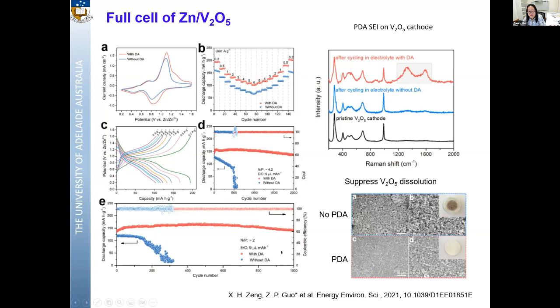Then the full cell, we can see with a low NP ratio, lean electrolyte can be charge-discharged for 1,000 cycles with capacity retention about 150 milliampere hour per gram. So apparently, this organic SEI helps to achieve a dendrite-free zinc anode, significantly improves the reversibility of the anode, and also suppresses cathode dissolution, helping to maintain the reversibility of the cathode as well. Combined together, it can achieve very good full cell performance.